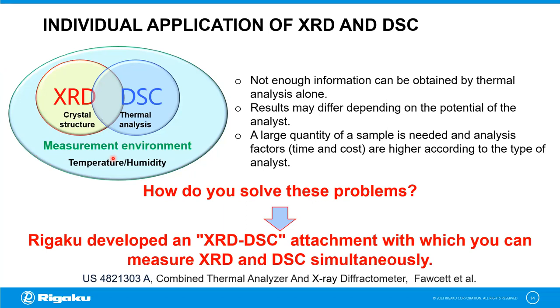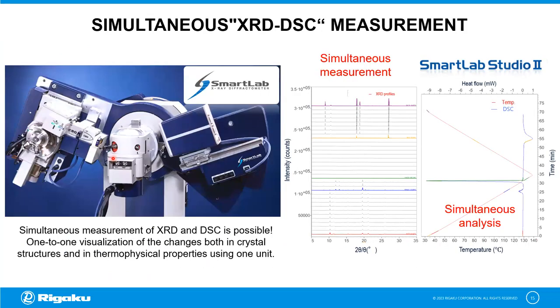So this idea is not new. We've implemented it in a modern format that makes it much more useful. So here is a simultaneous XRD-DSC instrument. We see the attachment here on a SmartLab. We have a rotating anode source, crossbeam optics here, CBO, and the attachment here, which provides the ability to have below room temperature, above room temperature, humidity control, as well as gas flow control. And then a HyPix-3000 detector, which allows us to collect diffraction patterns very, very quickly.